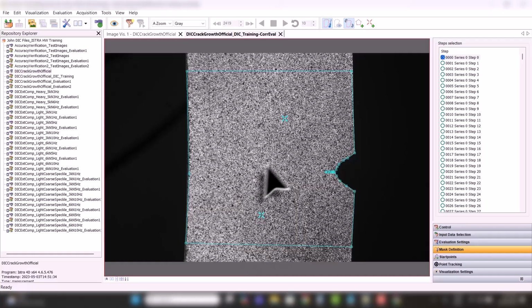Well, once you have a crack that's separating these 2 areas, these 2 distinct regions, what will most likely happen is it won't correlate past the crack after some point. The crack creates these 2 different regions, and it branches off from here or here, and it doesn't correlate past the crack. And so this gets uncorrelated. So here we need 2 start points.